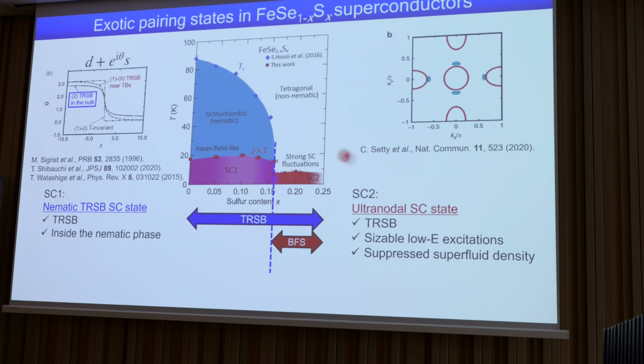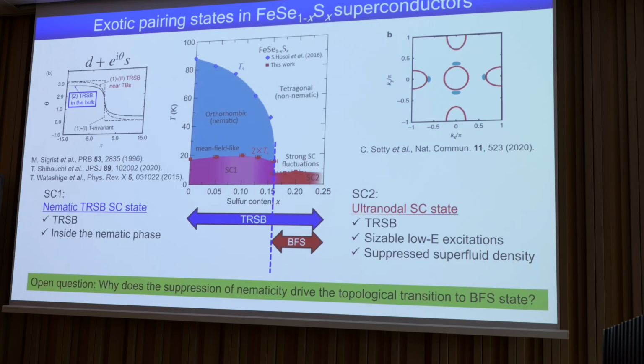But in the SC2 phase, which seems completely different, we still have evidence for time reversal symmetry breaking and evidence for Bogoliubov Fermi surface. So this is quite unusual. It's an open question why this suppression of nematicity can drive this topological transition to a Bogoliubov Fermi surface. I think there are many theories here, and I hope somebody can help us understand this behavior.